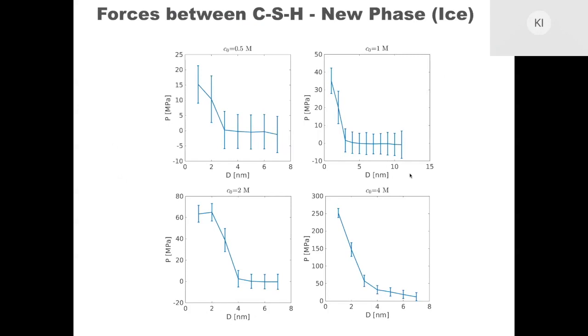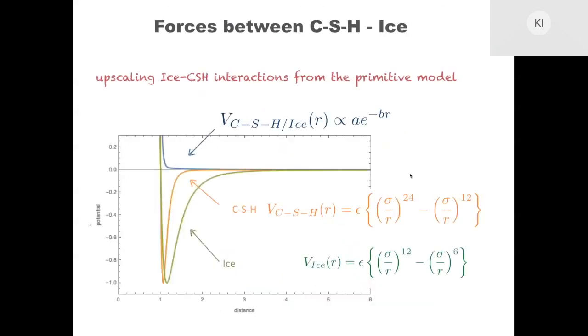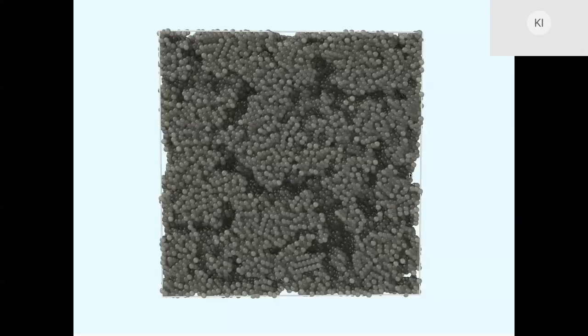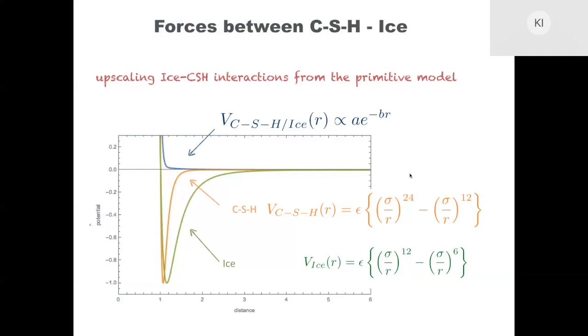So once we had these pressures, we can turn this pressure into an interaction potential between grains of ice and grains of CSH. So now we go to the next step of the simulation, where we have the sample of cement that you saw before with the cement grains. The cement grains interact with the CSH interaction as before, and now we will introduce ice grains that have an ice-ice interaction such that they can build a solid of ice that has the right mechanical properties of ice. And at the same time, we have an interaction between the 2 phases, the CSH and the ice, that came from the smaller scale simulations.